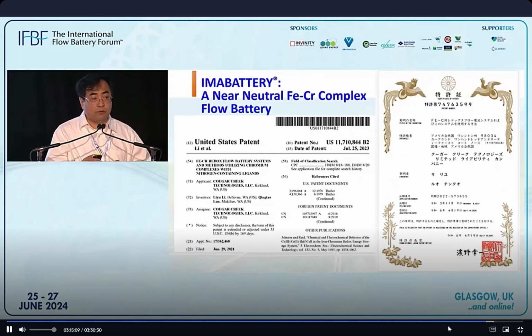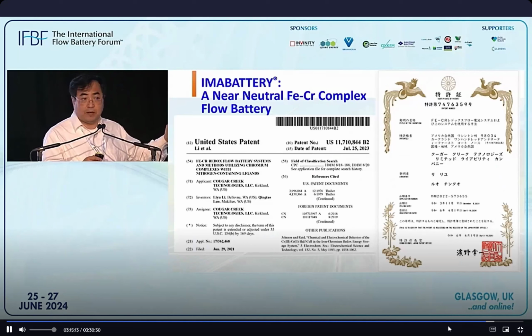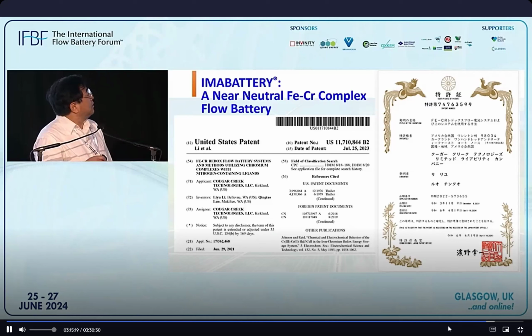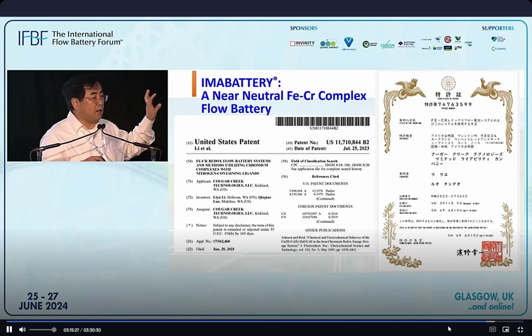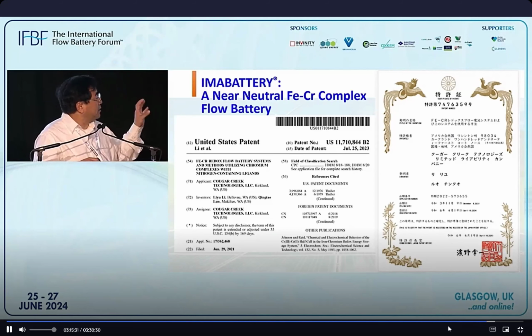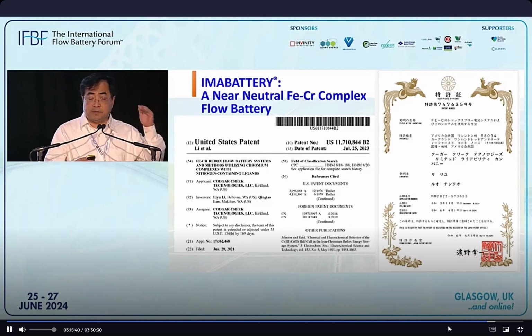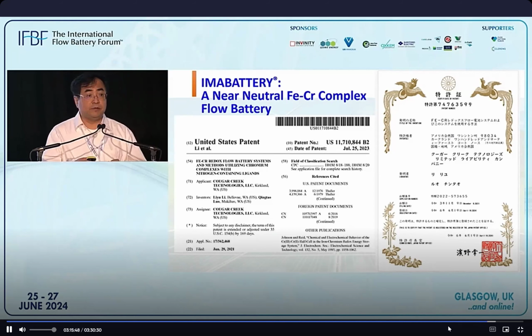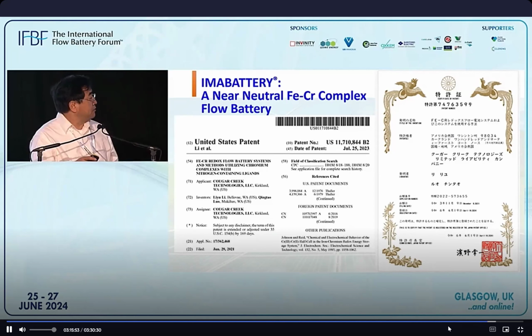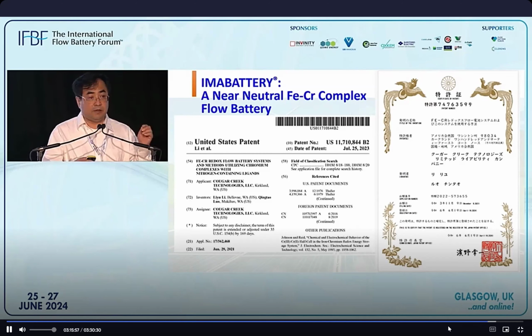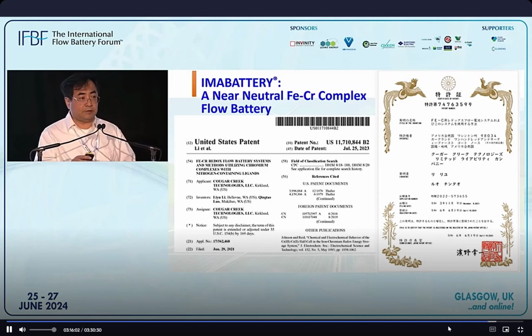So why we are working on this one is we made two major developments, improvements in this system. The number one is we make a near neutral complex system. We put nitrogen containing ligands to complex the chromium. So we make that complex and then largely improve the electrochemical reactivity. In order to put the nitrogen ligands onto the chromium cations, you have to reduce the proton concentration in the solution, which is not a bad thing. And the second thing is, after you reduce the proton concentration, you cannot use an ionic membrane like Nafion anymore. You have to use something that can transport all the ions in the solution. Then we get a separator which is much lower cost.